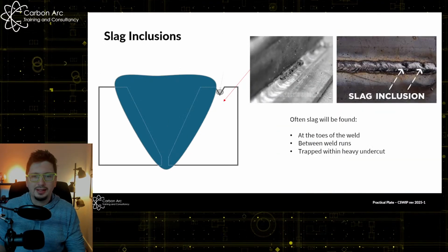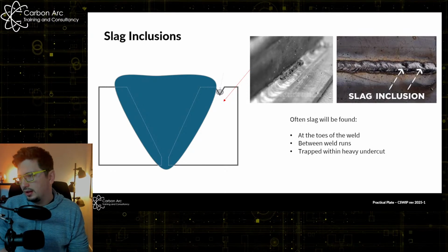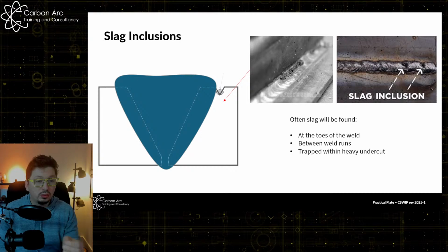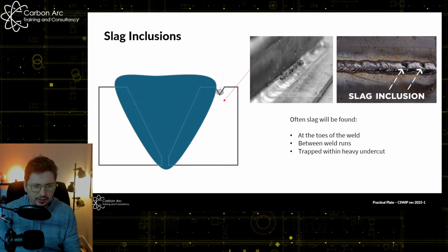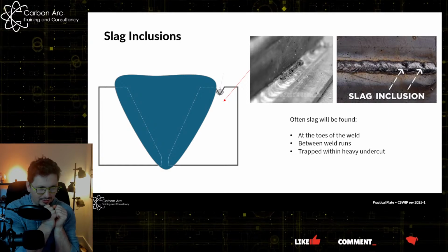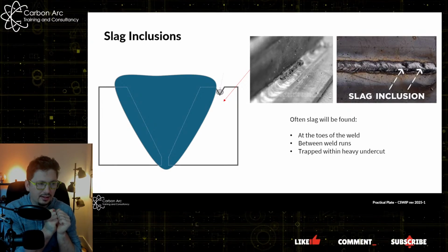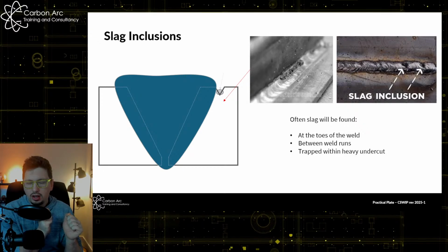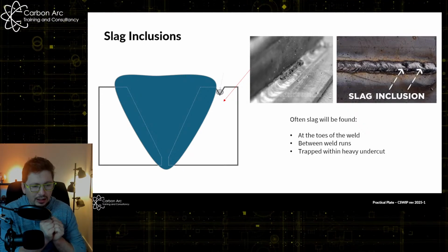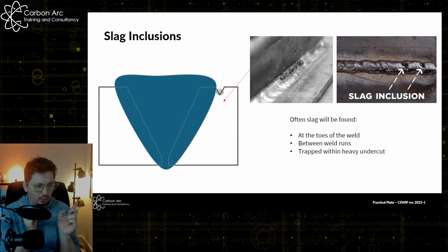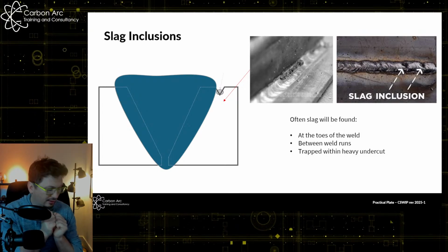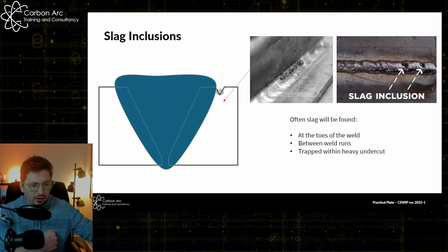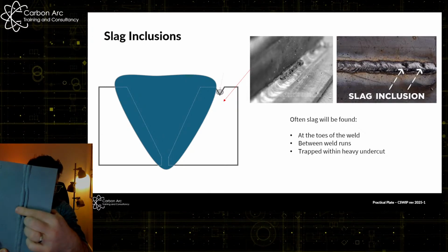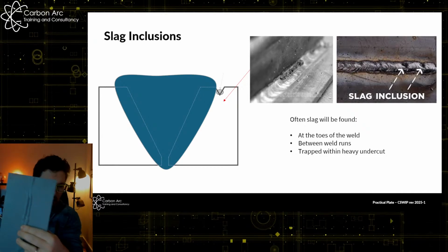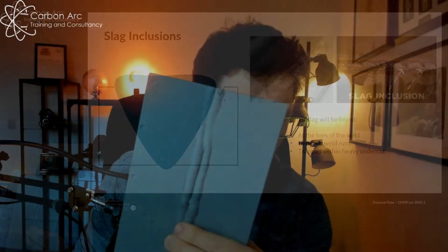Right. So here we've got slag inclusions. Now, slag inclusions are going to occur inside of another defect normally, something that can hold the slag in place and push it forward. So for this, we're normally looking on the toes of the welds or somewhere we can get trapped inside. Like I said, when we look at our sample here and we've got the lack of interrun fusion, potentially we're going to have a load of slag running down the internals here, okay?